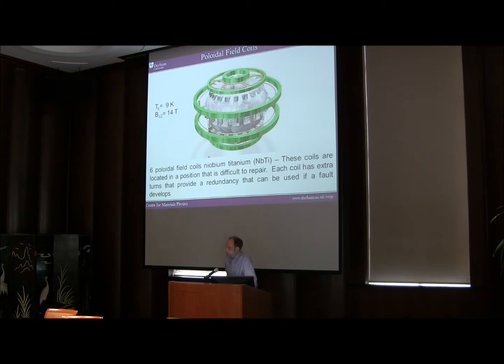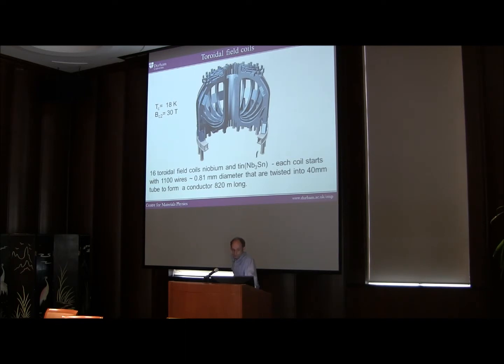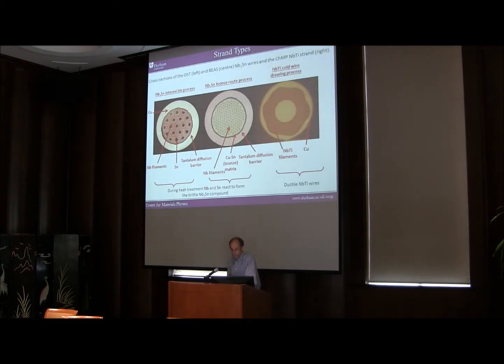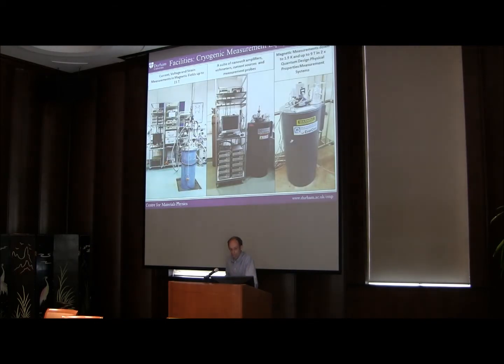This material, you have to get it down to temperatures of below 9 Kelvin in order to get it to superconduct properly. The niobium tin material used for the toroidal coils is a little less demanding. You need to be below 18 Kelvin for those to superconduct. That's what they look like if you look at cross sections of them. So these two pictures on the left-hand side there show the niobium tin superconductors used in the toroidal coils. There's two manufacturers of those, so they have two slightly different forms, and then the other superconductors, the niobium titanium ones, look very different in their format or in their making.